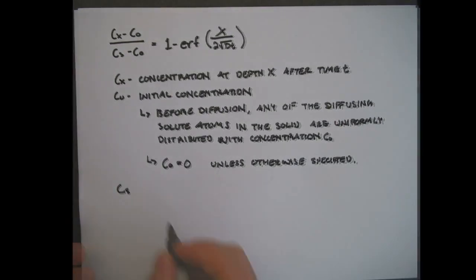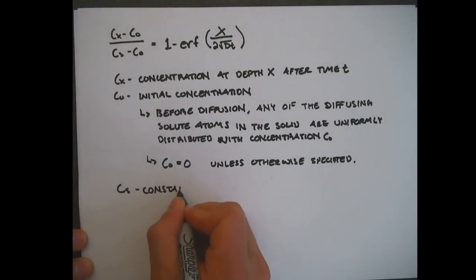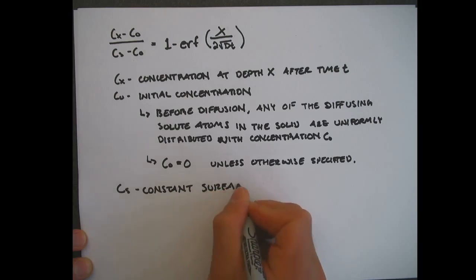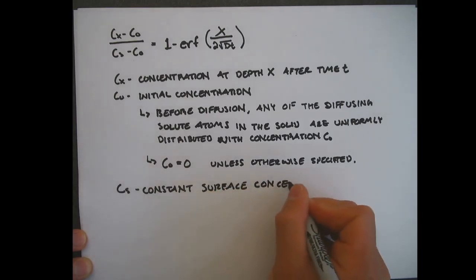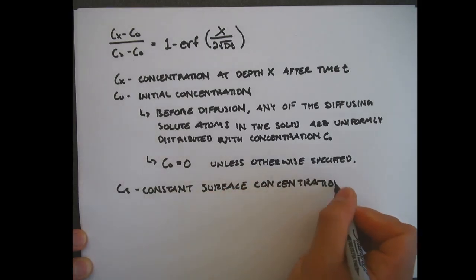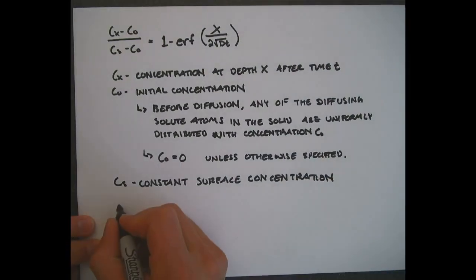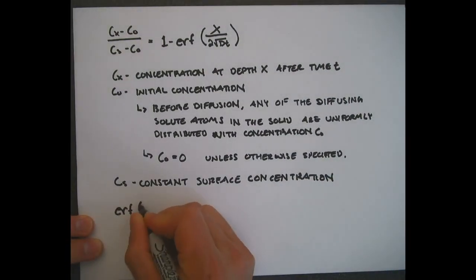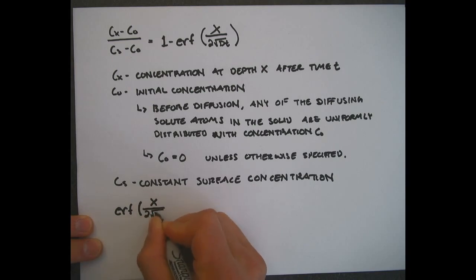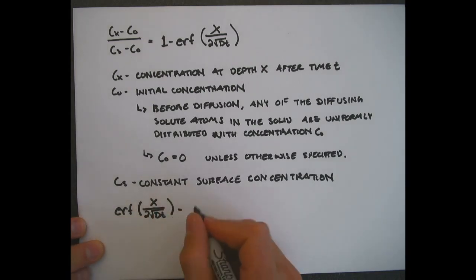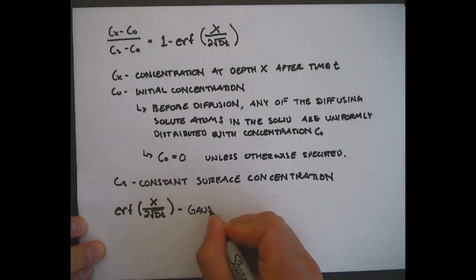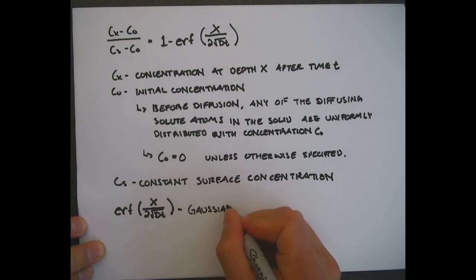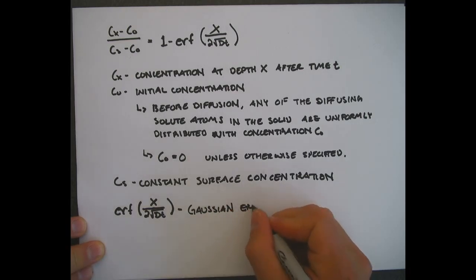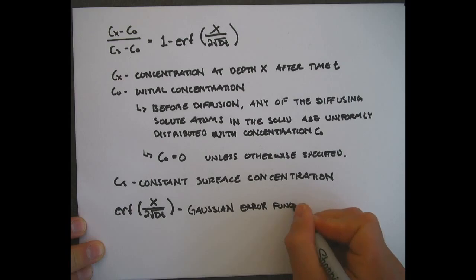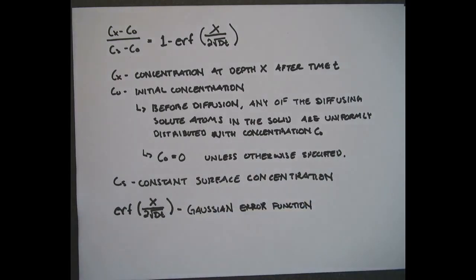This leads me to our last variable to define, and this is the C sub s, where that is the concentration on the surface of the solid. The last part of this formula I want to specify is the error function of x over 2 times the square root of Dt. This is the Gaussian error function. It is a measurement theory using probability and statistics. It's a very good estimation at a particular value.